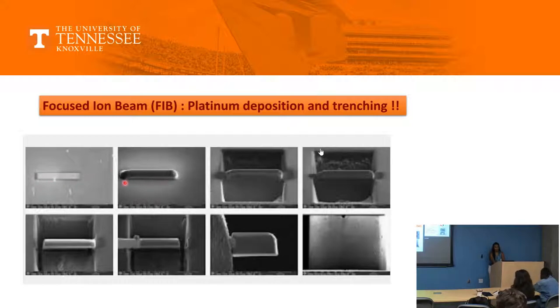Now you want that underneath this platinum, whatever the material is, you are able to take it out. To do that, you create two grooves. And for that, you use a very high energy gun. And you are constantly cleaning your sample while taking it out.